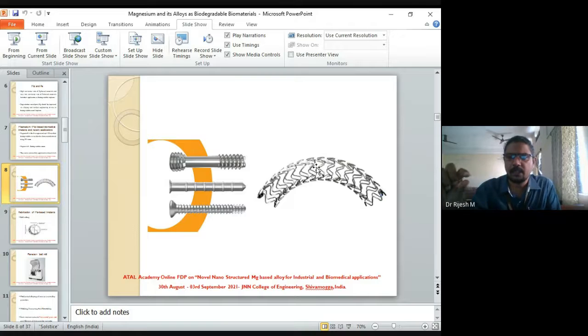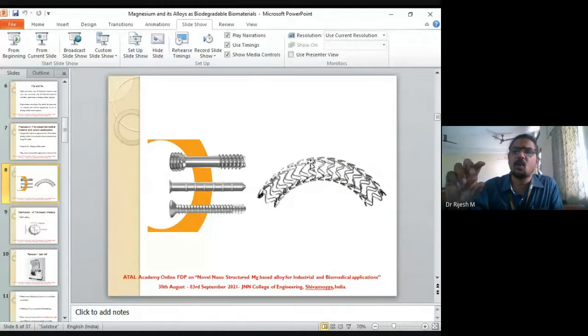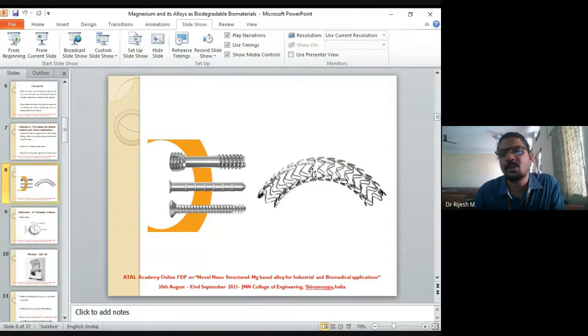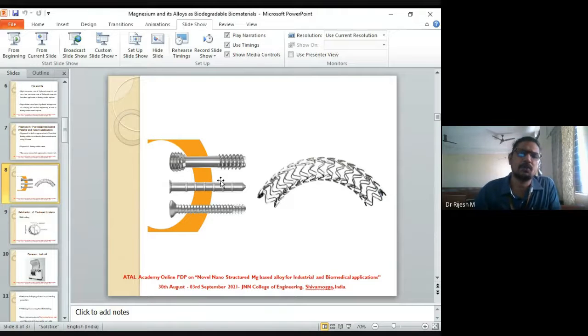You have a block in the artery, you insert the stent, inflate it and make it bigger, and that stent stays there for a longer time. Thus, you are increasing the diameter of the wall, where your heart functions much better. So the stent will remain there for a longer time, giving a good opening for the wall with a very good diameter. I don't want my stent to collapse at any point of time, and I want my stent to be rigid and be there. Being a metal with low weight and high strength, this is an ideal material for a stent. At the same time, since magnesium screws release Mg plus ions, they are good in this aspect also.